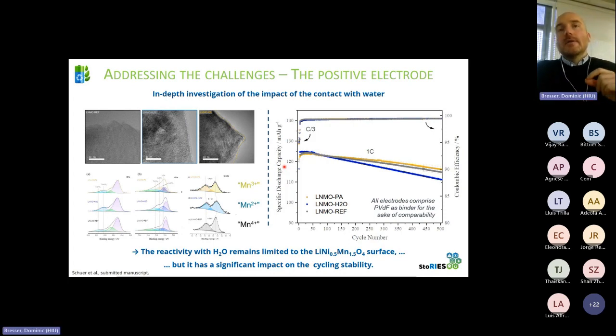But what is apparently difficult in such cases is to get to such thin layers, right? So usually then we're talking about 2 or 3 nanometers, more or less. But also this turned out beneficial. So let's say generally any kind of very thin metal phosphate layer that you can deposit on these particles has a beneficial effect if properly done. But phosphoric acid just does the same trick.